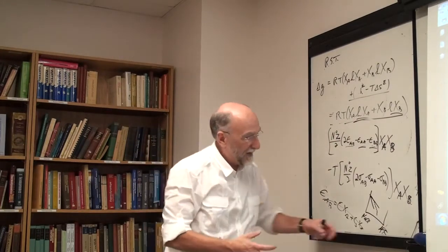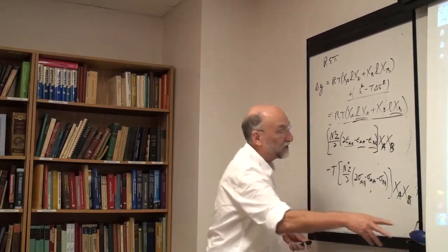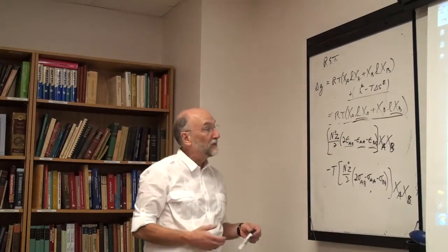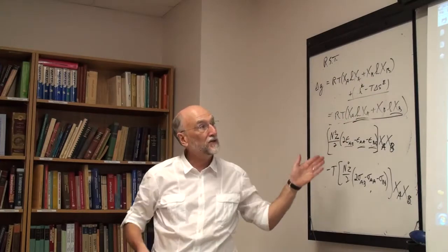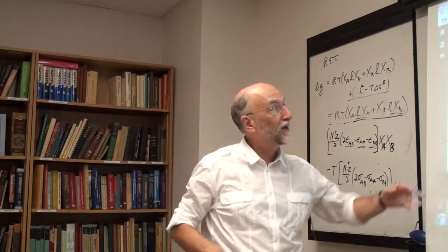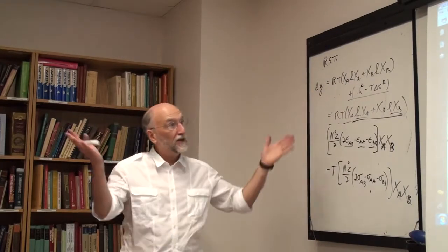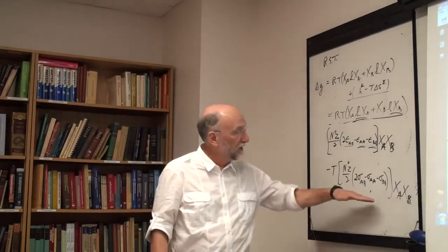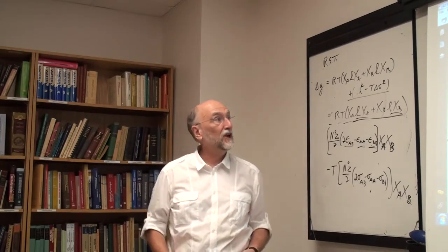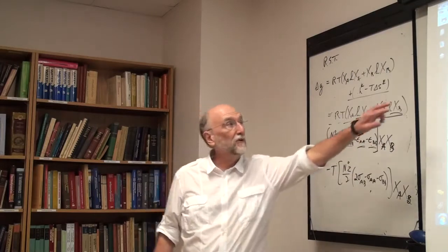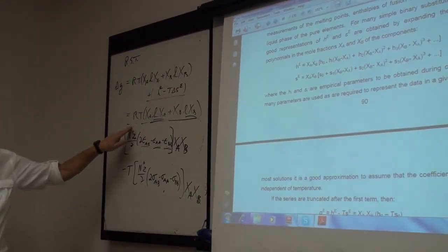Okay, so if you really have deviations from ideality where the configurational entropy is no longer roughly a random mixture, this is not the best way to represent your solution. You might, in the central composition regions, manage to fit it reasonably, simply because you can fit all sorts of things to polynomials, but certainly in the limiting composition regions, it's really impossible to fit, because you're not doing your configurational entropy right.